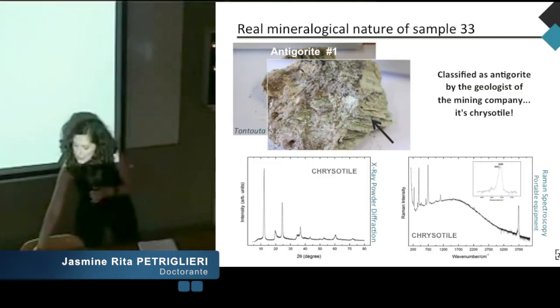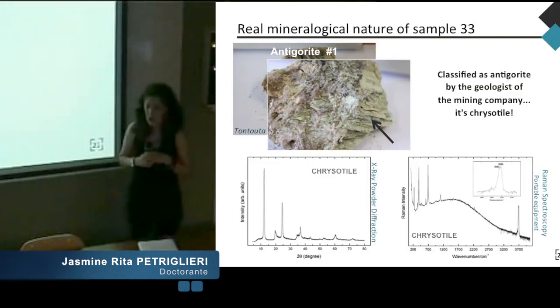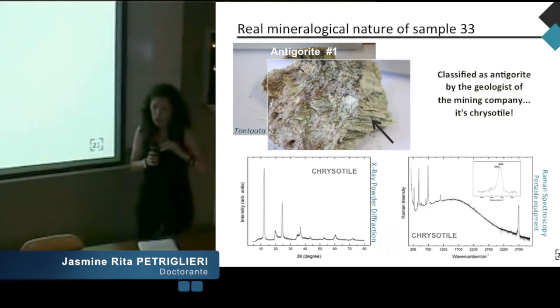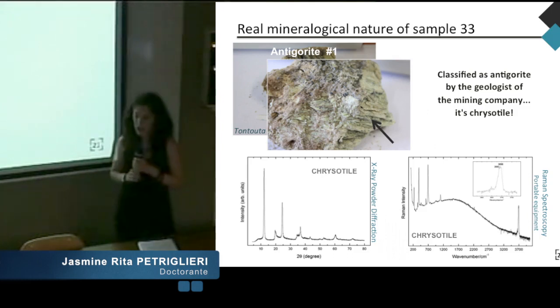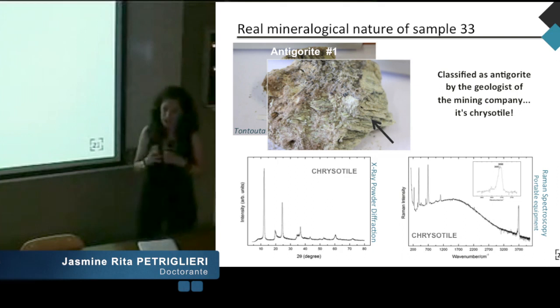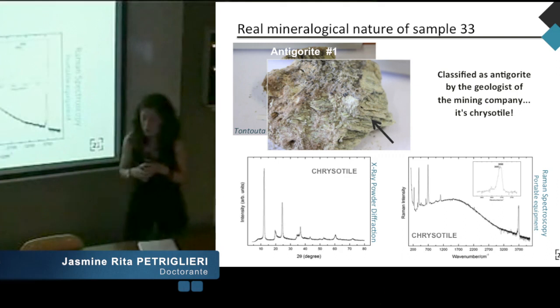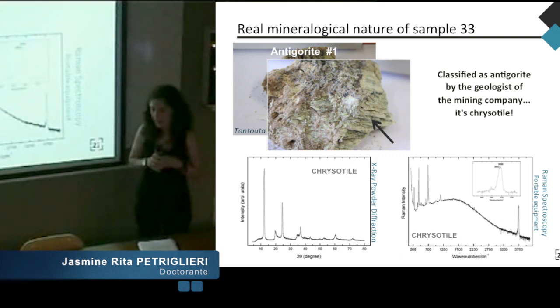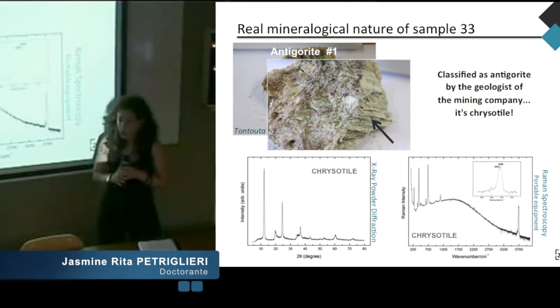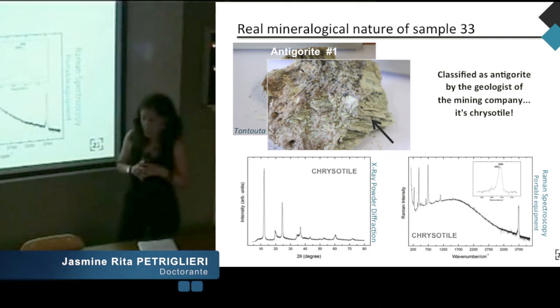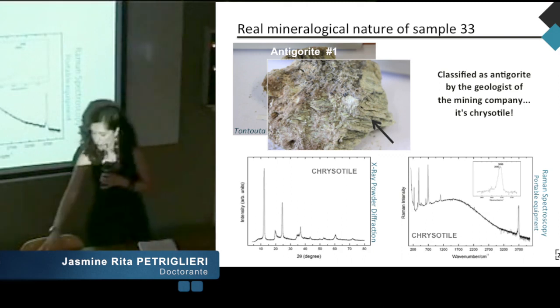I will describe sample 33, which is the most emblematic in this context. At the hand scale it consists of the overlapping of well-formed lamellae characterized by color ranging from green to white. The first preliminary X-ray powder diffraction and portable Raman investigation confirmed that this is chrysotile.